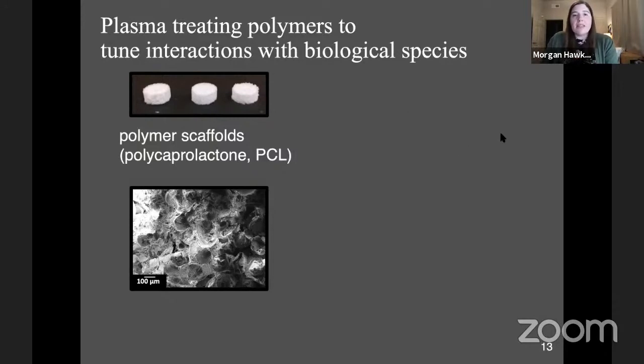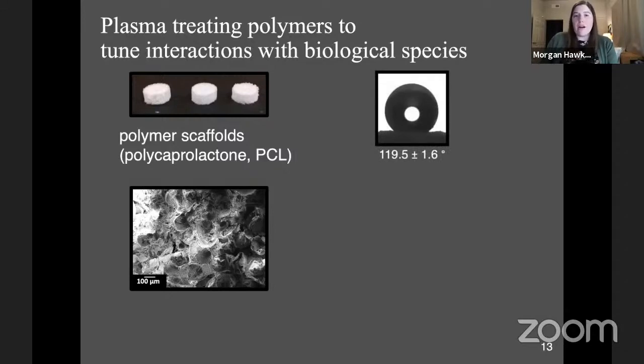So the problem with this polymer is that it's incredibly hydrophobic. And this is an image taken using a technique called water contact angle goniometry. So a water drop is placed on the surface and the angle between the drop and the surface is measured. So what you're looking at here is a side-on view of the water drop on the surface, showing it beading up, similar to what you would see in like a Teflon pan or on the surface of a Gore-Tex raincoat.